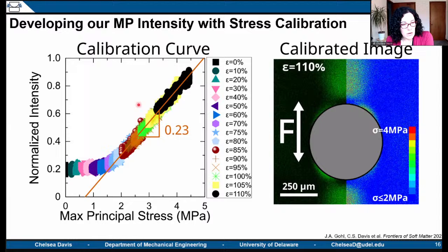In the region we care about, I'm going to argue that it is linear. Down here, I also fully agree that it is nonlinear. But this is our threshold. This is our fluorescence background. Our mechanophore hasn't really started turning on here. So I don't think that trying to get really fiddly about catching this part of our curve is going to buy us enough of an accuracy trade-off to not just treat this as linear. This is before the mechanophore has activated, so we just basically throw this away.